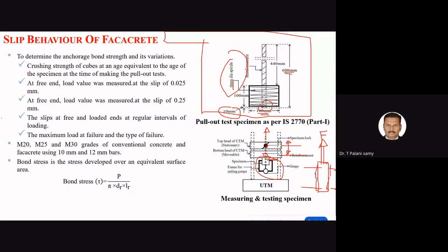So how the free end, the load values was measured at the slip of 0.25 mm we can measure, and the slips at the free and loaded ends at regular intervals of loading. The maximum load, failure and the type of failure for M20, M25, M30 grades conventional concrete and concrete using 10 mm, 12 mm bars.